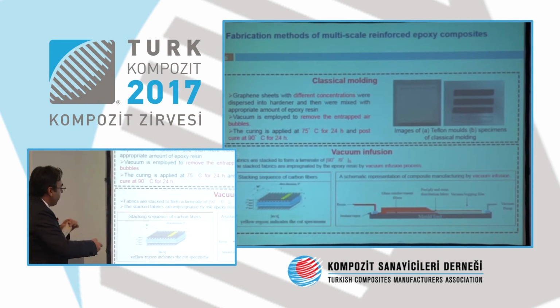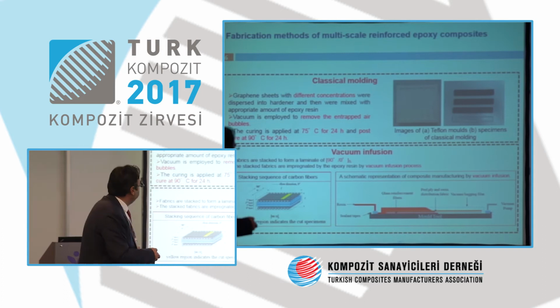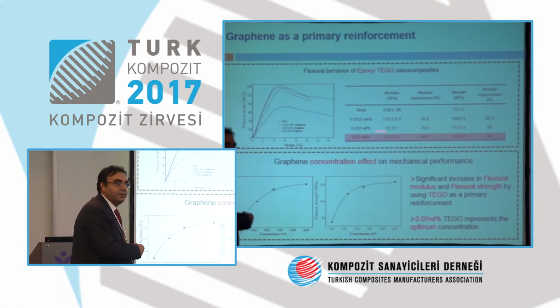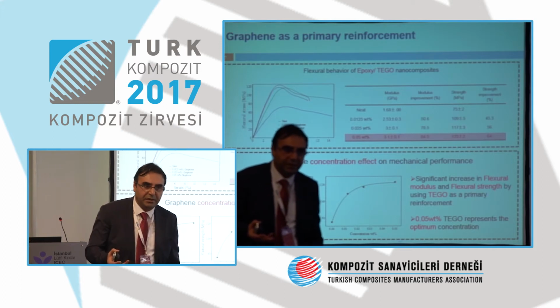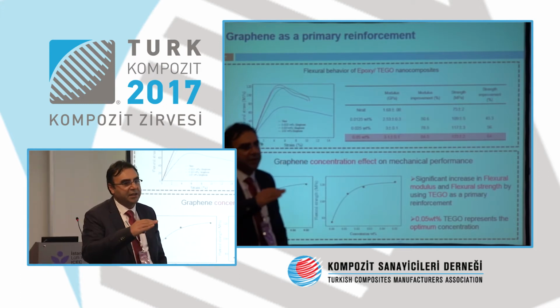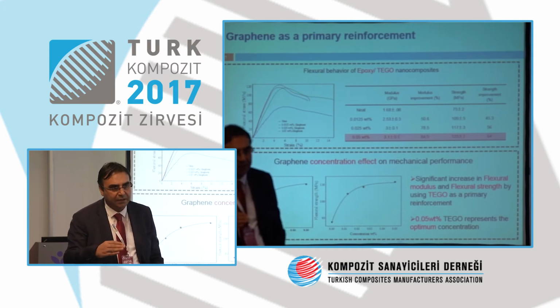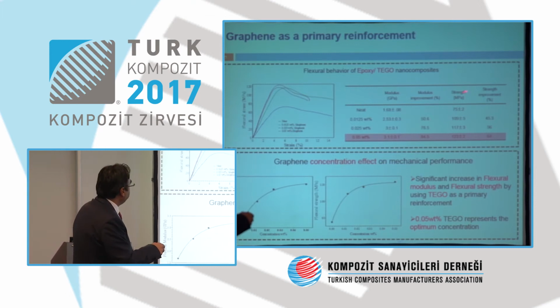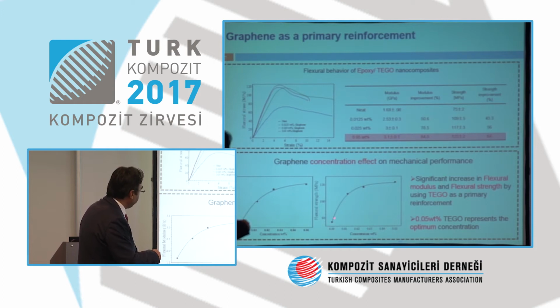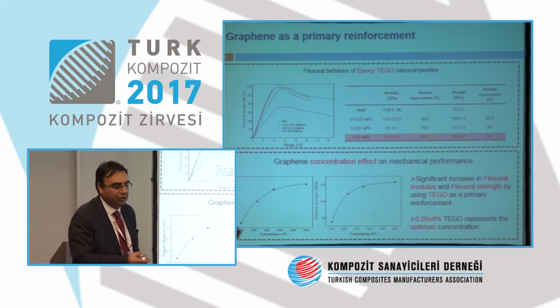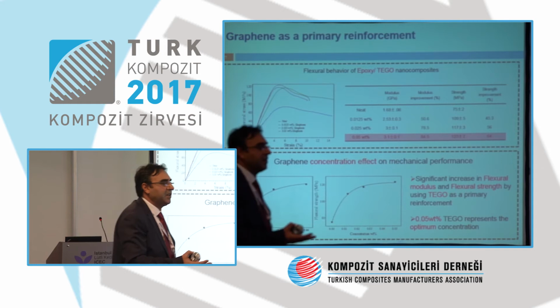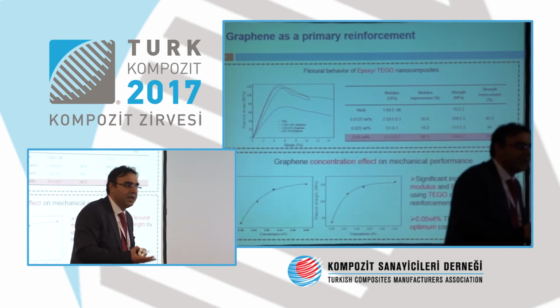First, I will talk about the results of this one, and then you may say that anything you add is going to improve the performance of the composite, so what is new about it? That might be a very logical question, because you are adding a reinforcement to the neat material, and you are increasing the mechanical performance because you are increasing its toughness. Effectively the epoxy is a very brittle resin, and when you add the graphene, it creates obstacles for the crack to propagate. And then you are increasing the toughness, and this is what you have. You see that the strength can be improved with an amount of 0.05 weight percent, and adding beyond that is not going to make any changes. This is effectively your percolation threshold, and one can find a lot of literature activity on that.